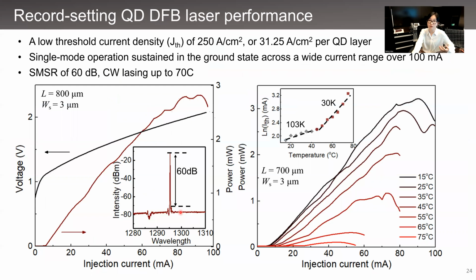So this figure shows the representative LI curves for a laser bar with a 3 micrometer wide gain mesa. So the laser had a threshold current of 6 milliamp at room temperature, which corresponds to a pretty low threshold current density of just around 30 amp per square centimeter for each of the quantum dot layers. And this is the representative emission spectrum, which shows single mode operation with a maximal side mode suppression ratio of more than 60 dB. And here we show the temperature LI curves. We got CW lasing up to 75 degrees C and a characteristic temperature around 103 Kelvin in the low temperature range.